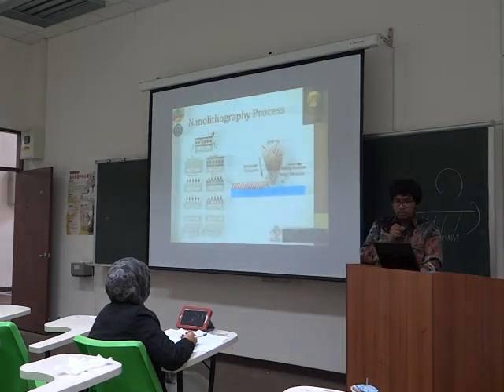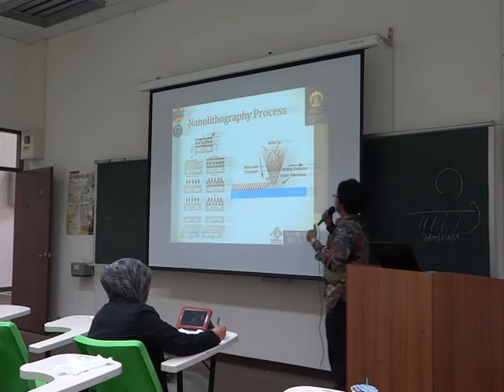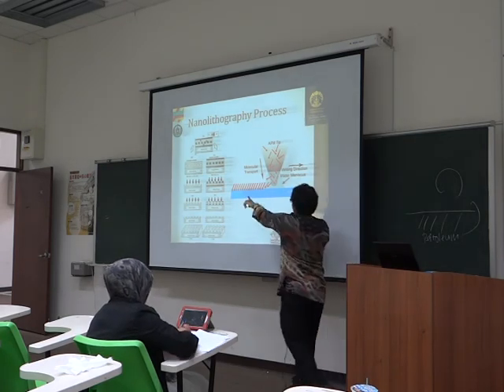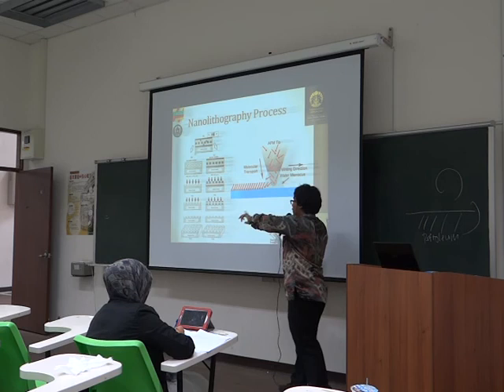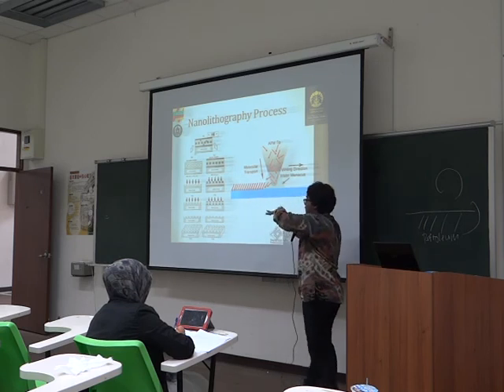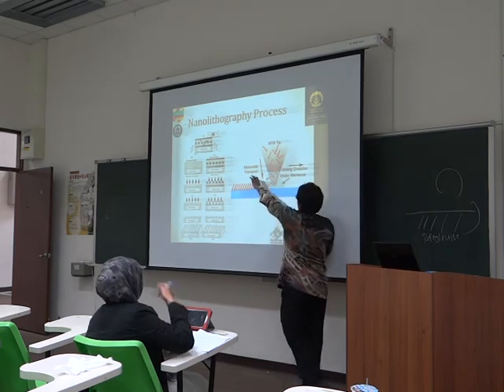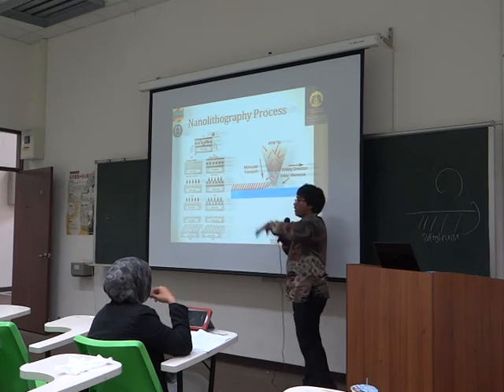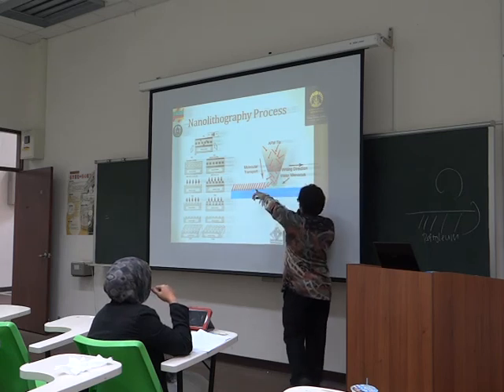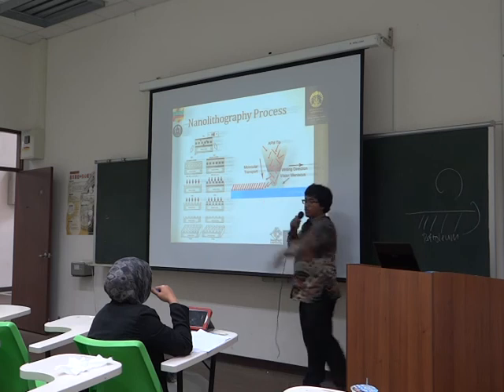After we made it, we use it in the nanolithography process. So we put all of the copper nanoparticles here. After that, we use PECVD again to make the wafer up here. So it's like a burger: silicon, copper nanoparticle, and then silicon again.